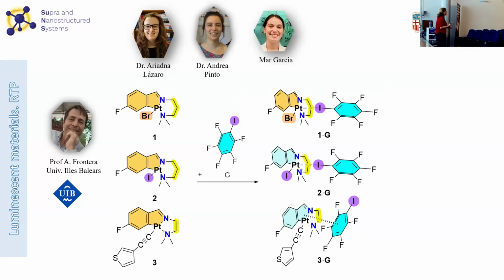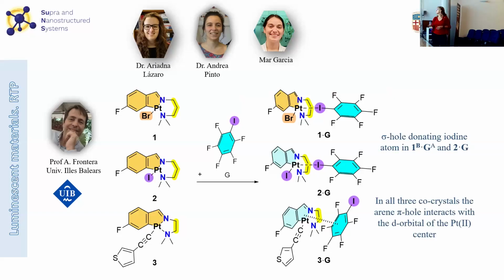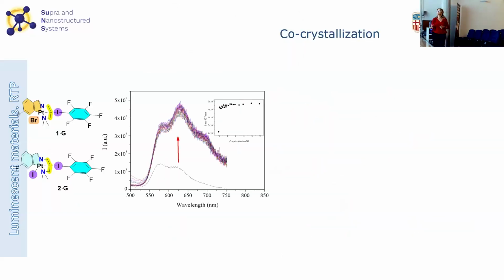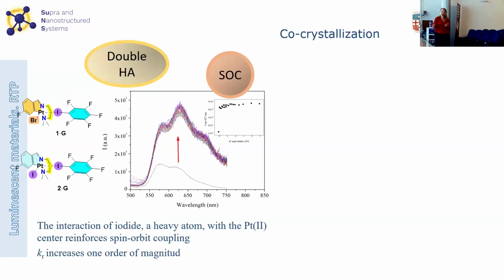How does this affect the resulting luminescence? Well, this is what we explored. We made a titration, adding increasing amounts of the guest to a solution of the host, the platinum sample. And we observe that in the cases having this direct platinum-iodine bond, there is a clear enhancement with just 0.1 equivalent of the guest in the solution. So there is a clear improvement of the emission quantum yields. And this is due to an increase of the radiative rate constant by 1 order of magnitude.